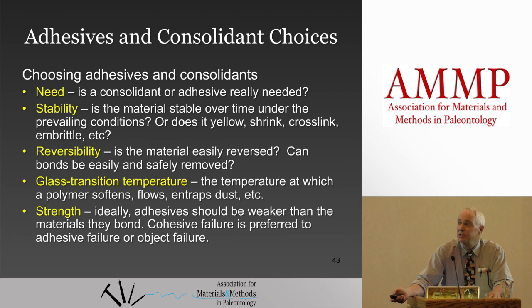And strength. Ideally, adhesives should be weaker than the materials they bond. Cohesive failure, where the adhesive fails within the adhesive itself, is far preferred to adhesive failure or object failure, where the adhesive pulls away from the specimen or the specimen fails. So a lot of times people think, well, I need a really strong adhesive. Well, you probably don't. Adhesive joins really should not rely on the adhesive itself to prevent failure. That's where supporting structures, which you'll hear about more here in a short time, come in.